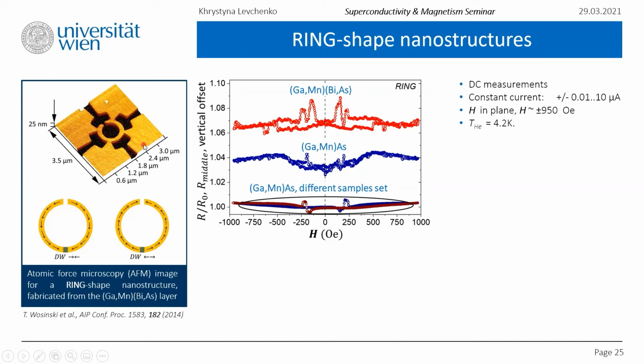And we were able to observe the high and low states of the resistance. They were achieved through the additional contribution the charge carriers gain while passing through the domain wall area. This additional contribution manifested itself as a difference in resistance of 20-30 ohms for the gallium manganese arsenide. But as you may see, this was drastically enhanced in the structures with bismuth, at least by 2-3 times. And this is one of the reasons why we used bismuth in our structures.